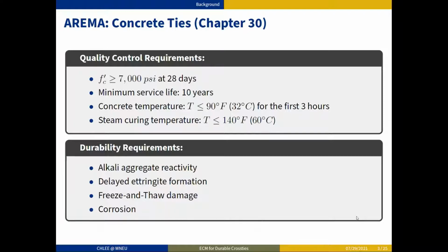In addition, AREMA requires several durability requirements about the alkali aggregate reactivity, delayed ettringite formation, freeze and thaw damage, and corrosion. However, it's really hard to follow those rules because they provided the related ASTM standards. However, ASTM does not require any specific structural performance related to the durability damage.